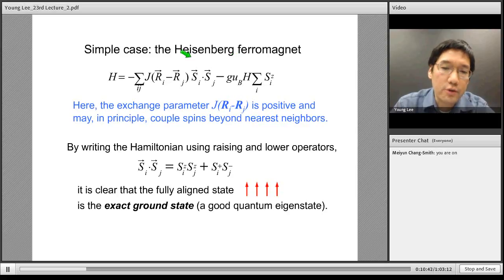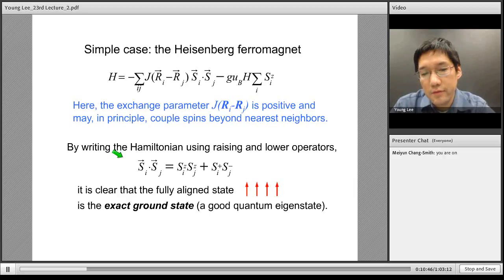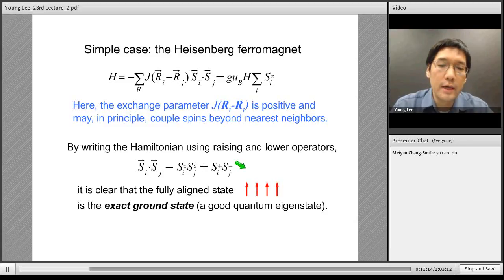Now, this Si dot Sj term here, we can rewrite in terms of the Sz operators and raising and lowering operators. And this is a very standard decomposition. And when you apply this operator on a fully aligned state, and classically that's what we expect, right? If the energy is telling us neighboring spins want to be parallel, then the low energy state will be when all of the spins are parallel and pointing in the same direction. So that's what we classically expect. And we can see when we operate with this Si dot Sj operator, this lowering operator will annihilate, and Si^z Sj^z will just give us S squared. So we do have a proper eigenstate. So this also turns out to be the exact ground state. So this fully polarized all up state is a good quantum eigenstate. And there's really no surprise there.